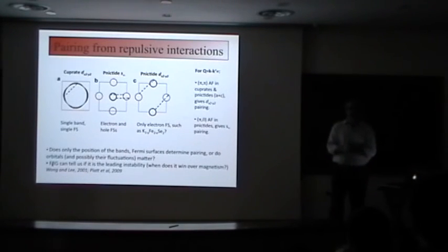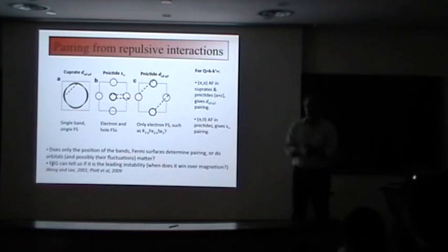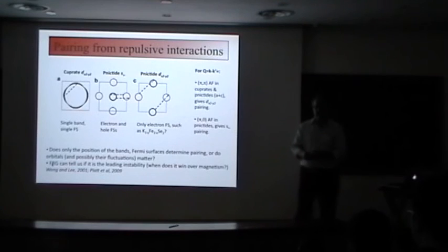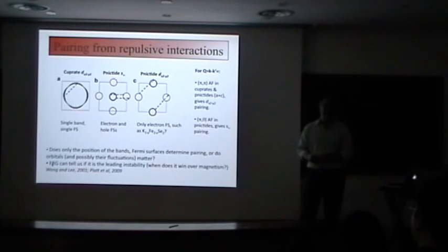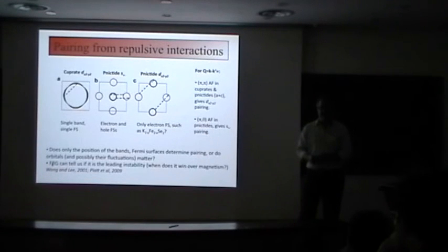So you showed the Fisher results for the transport anisotropy, particularly in the temperature range above the structural transition. The reasoning of Fisher and collaborators was basically that there was a strong nematic susceptibility in the system, where if they applied a tiny stress with their anvil, whatever it was, they would see an anisotropy, which makes a lot of sense in many ways. But there are other experimental claims that have been presented, which suggest that it's actually a nematic order which exists above that structural transition and not just the nematic susceptibility.